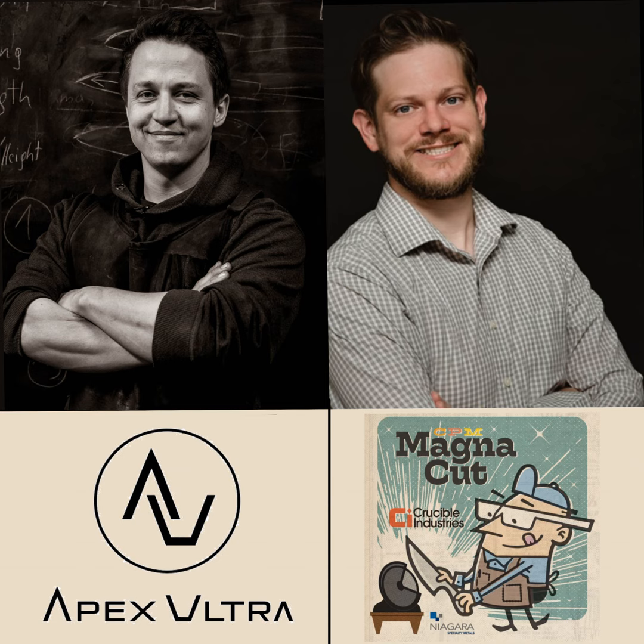That's what I was just going to say. That's usually the criteria where the industry decides to go to powder metallurgy. Nobody does it for fun, but usually you go to powder metallurgy if you're making steels that otherwise would form such terrible large carbides or segregations that you can't just produce them in a conventional method. So now you can put in more alloying elements and go through powder metallurgy, and it still works out because of the process, because there's no time for making large carbides.